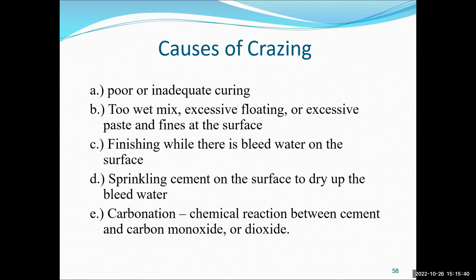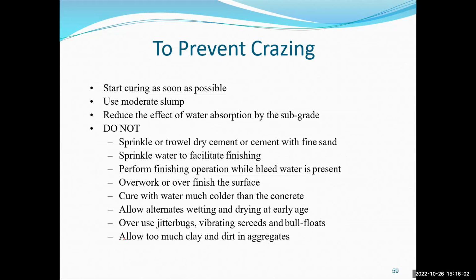Or some people do a very, very unhealthy practice: they sprinkle cement. They put new cement on top, sprinkle cement and put some water, in order to mix it up and make it easy. This is a big no, it will create a problem. And carbonation, whenever the concrete is fresh, if carbon dioxide is mixed with the water, that will cause carbonic acid and will cause this kind of mapping.